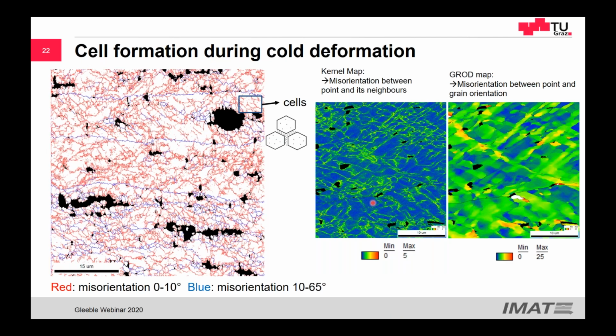So during cold deformation, we have a different situation. We also form some substructure. In this case, they are called cells. And these cells have this structure. So these blue are high angle grain boundaries, and the red ones are low angle grain boundaries. And you can see this type of cells formed all with some orientations.